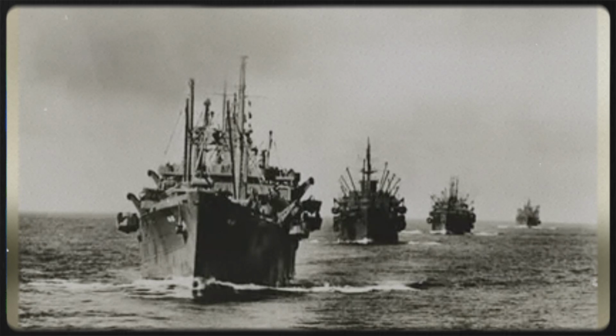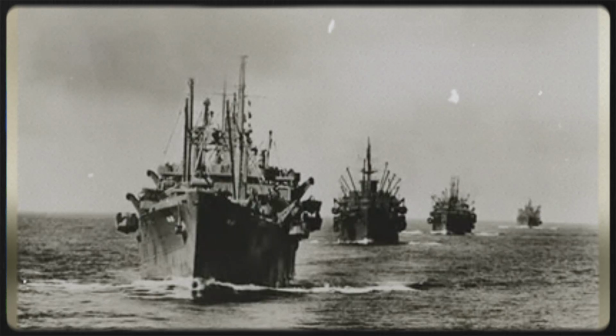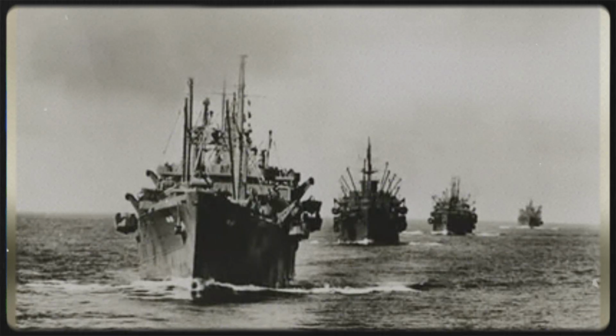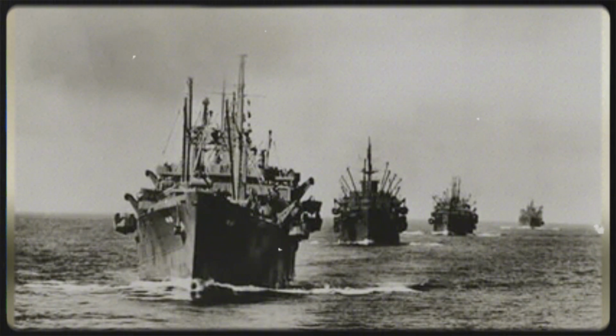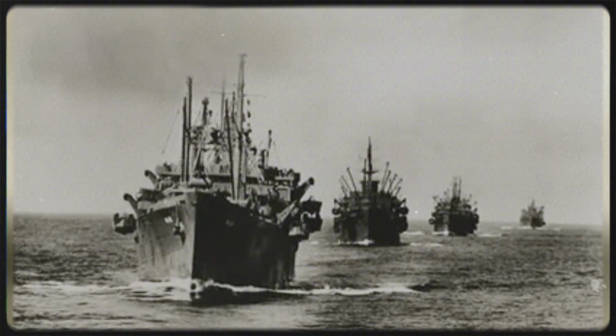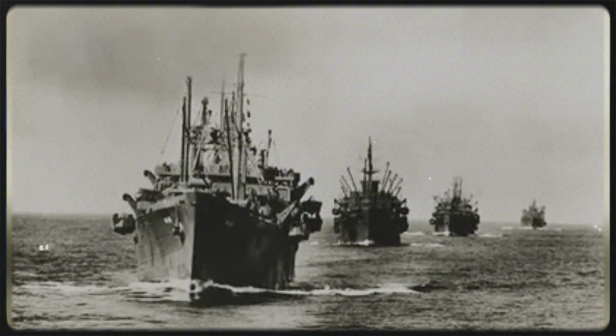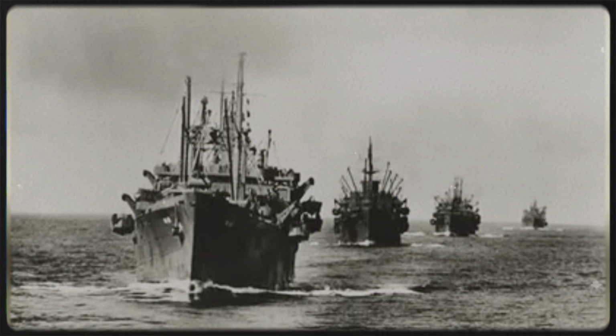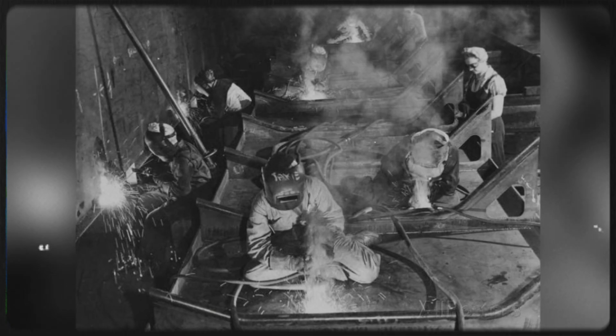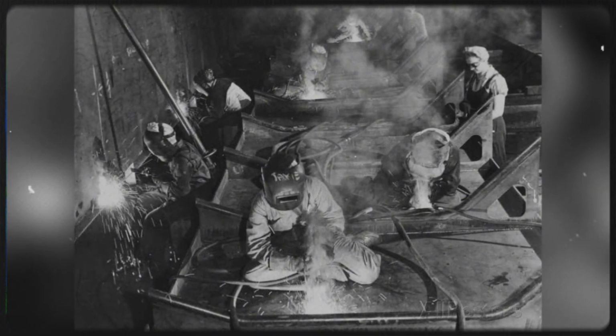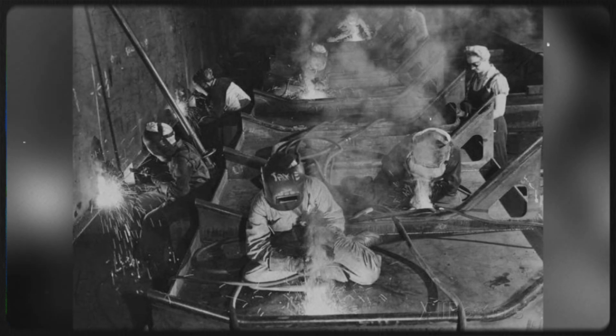By the end of January, 19 Liberty ships had suffered serious hull cracks, and 7 had broken completely apart. The statistical projection was terrifying. If the failure rate continued, the Allies would lose more tonnage to structural collapse than to U-boats, and the entire